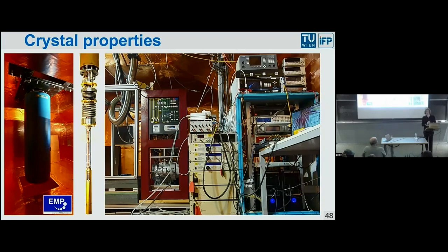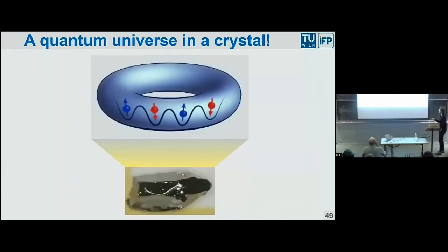So just to follow up then, did you then introduce a magnetic field on top of it? We can do that. Yes, and we did, of course. And then we see something very interesting, that this effect extends to finite magnetic fields. And you get a Hall signal that's very different from a normal Hall effect. A normal Hall effect is always anti-symmetric in field. But here it's a symmetric effect because the field isn't creating the effect. So the field is only, in fact, what it is doing